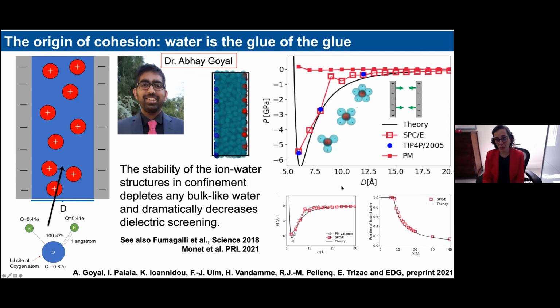Ultimately, as I said, we also did some tests with different water models, so you can see that the results do not depend on the specific water model we have used. And the theory allows us to abstract the basic origin of this behavior from the simulation. If we consider the correlations between the ions in this very strong coupling regime, and we compute the interactions between the two surfaces due to the presence of this stable ion-water structure, then we obtain the forces that we see in the simulations.